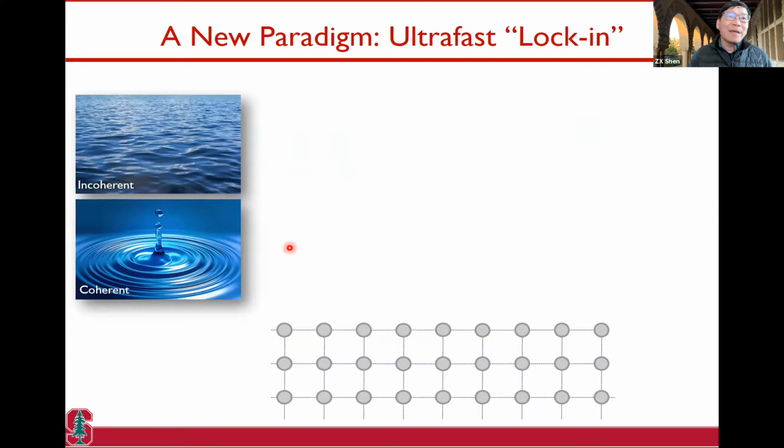So you can make a macroscopic measurement, but you cannot use that to make a microscopic measurement. So our goal was to push this lock-in technique into the terahertz regime and use the intrinsic frequency of the phonon in the system to generate a reference frequency, therefore to improve the signal to noise.